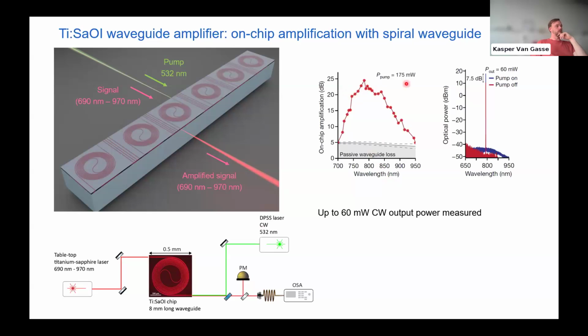Okay, so that was the gain bandwidth and gain per unit length. But we also want to understand, can we get actual power out of this system? The answer is yes. We can get up to about 60 milliwatts of output power and still achieve about 7 dB of gain. However, in this case, we were mainly limited by the fact that this was one of the first devices we ever made. We still had quite some passive losses. And on top of that, the cross-section of this waveguide is pretty tiny. I think we can easily do a few hundred milliwatts with a slightly larger cross-section.